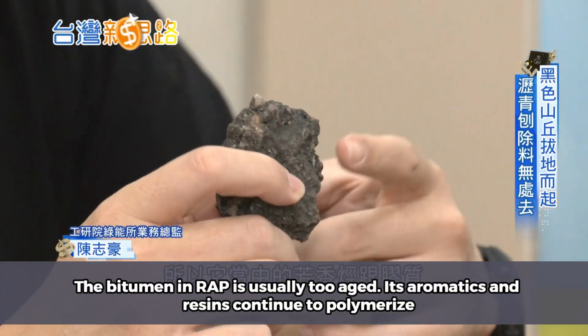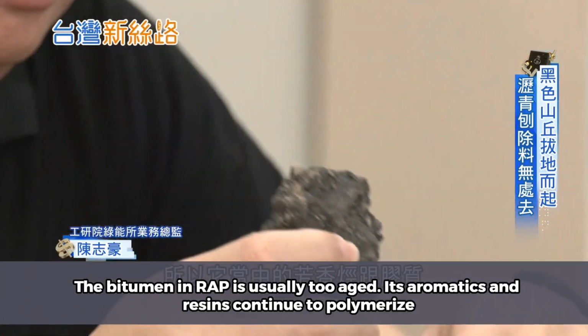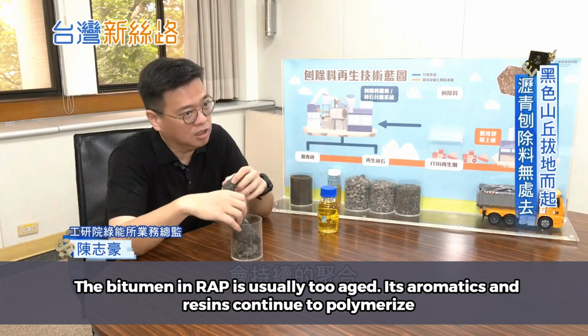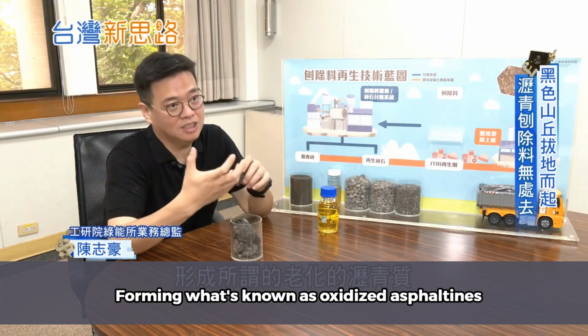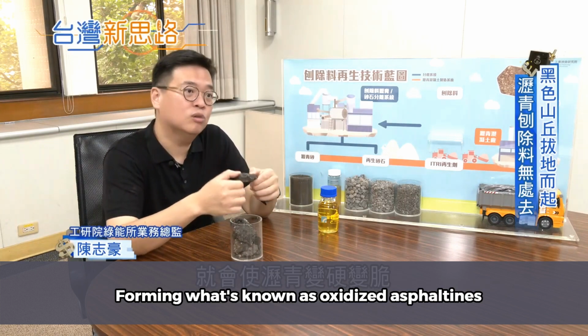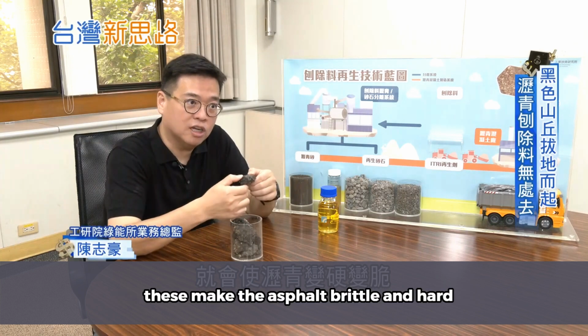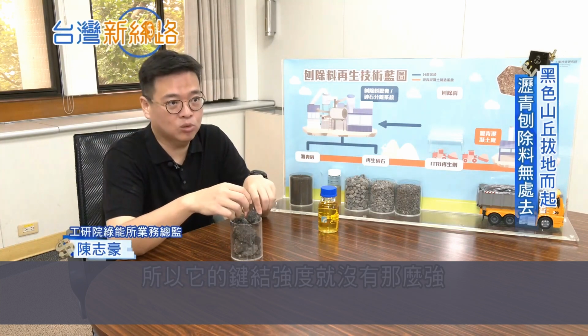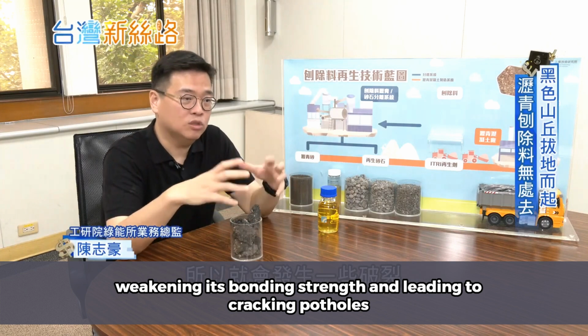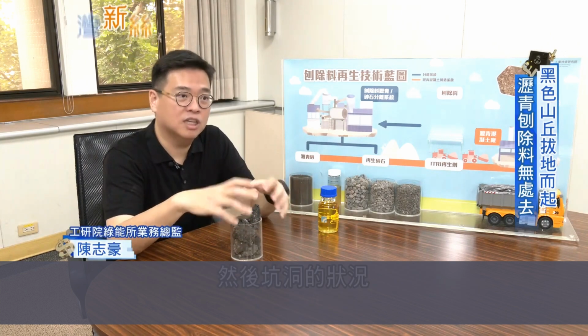The bitumen in RAP is usually too aged. Its aromatics and resins continue to polymerize, forming what's known as oxidized asphaltenes. These make the asphalt brittle and hard, weakening its bonding strength and leading to cracking and potholes.